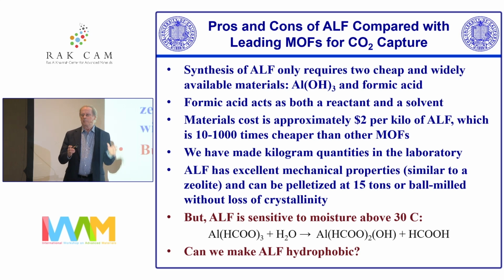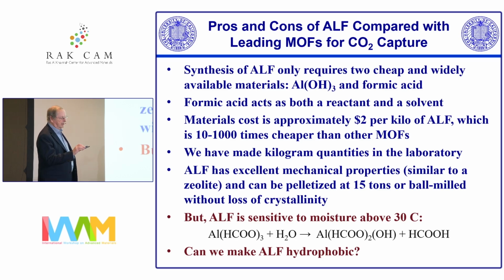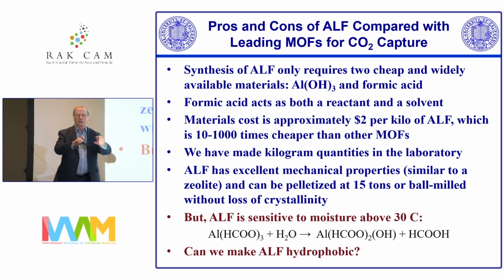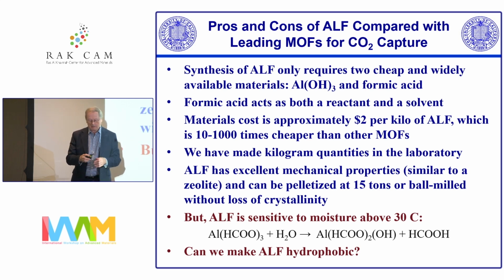A farmer with a bucket in Ras Al Khaimah could actually make this in a field. It's so easy to make, especially if you get the solar energy heating it up a little bit. So it's very easy to make. And one other thing I'll say about it, it has excellent mechanical properties, but it's sensitive to moisture above about 30 degrees C, and it hydrolyzes to a chain structure which has no porosity. So you obviously don't want that to happen.